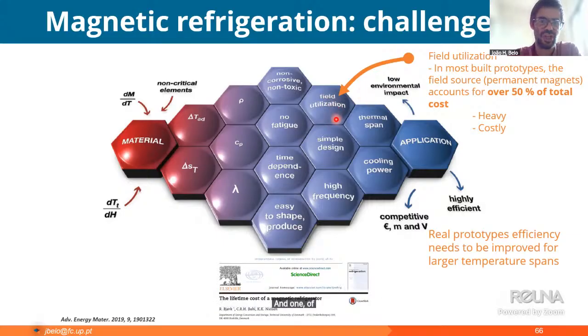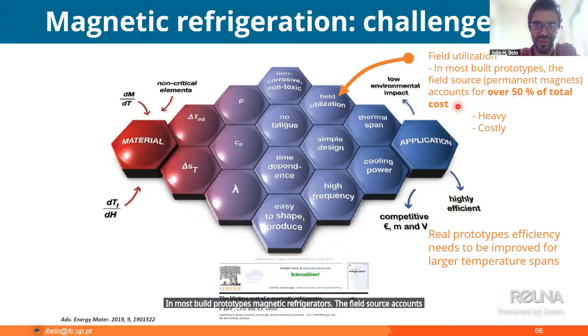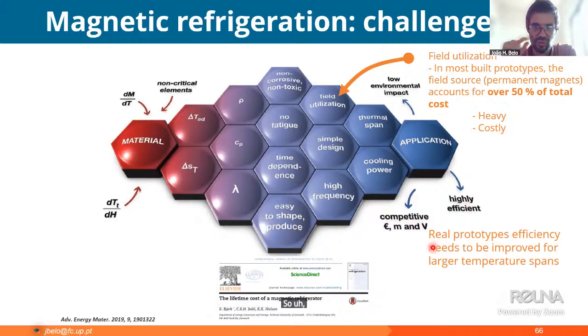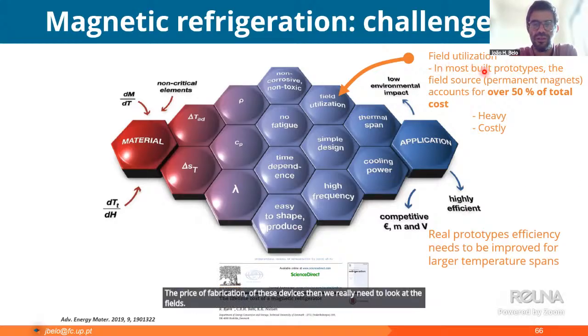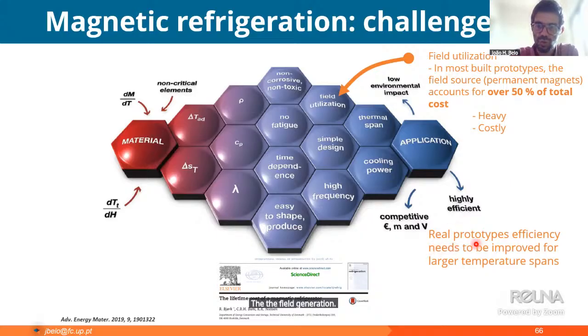One of the device's challenges is field utilization, meaning that in most built prototypes of magnetic refrigerators, the field source accounts for over 50% of the total cost of the prototype. Moreover, they are also very heavy and costly. So this is really a major issue in economic terms. If we need to decrease the price of fabrication of these devices, then we really need to look at the field generation. Also, on real prototypes, the efficiency needs to be improved to achieve larger temperature spans. You can check this 50% in the reference by Rasmus Bjørk.